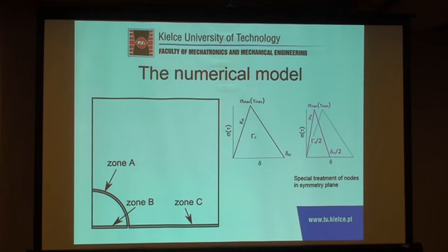The first one, the obvious one, is the reduction of the total energy of fracture by half. Then the initial stiffness of elements was doubled. The nodes creating the zones were shrunk to create a zero thickness zone, and to avoid uncontrolled movement of nodes connected to the symmetry plane in the horizontal direction, there were additional constraints. The movement of these nodes was connected with counterparts, partners connected to the matrix and the material of the inclusion.